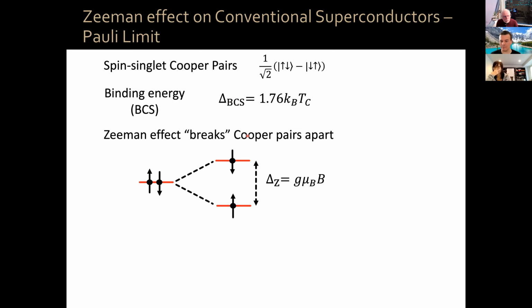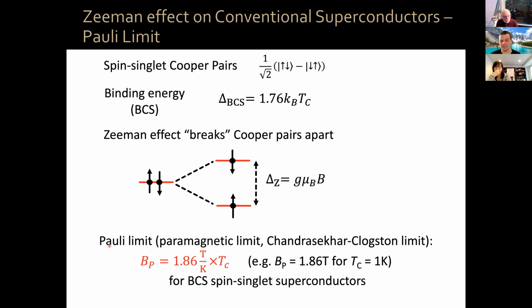If you put in numbers, you have that there is this thing called the Pauli limit, the paramagnetic limit, or the Chandrasekhar-Clogston limit, which tells you that superconductivity should be well gone by the time you reach a magnetic field of 1.86 Tesla per Kelvin times TC. So for a TC of 1 Kelvin, superconductivity should be well gone by 1.86 Tesla, okay? That's for BCS spin-singlet superconductors.